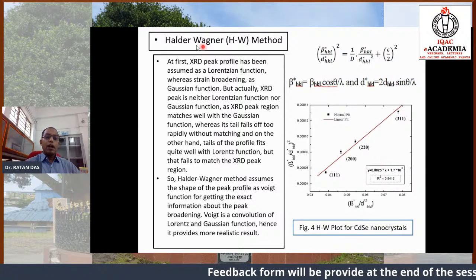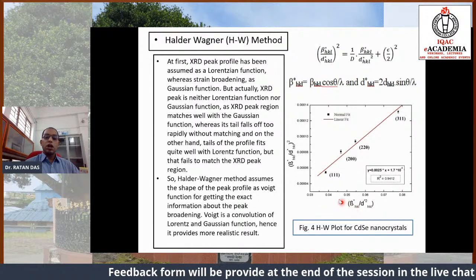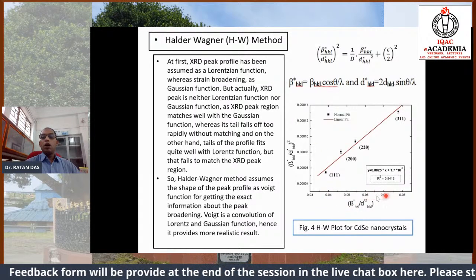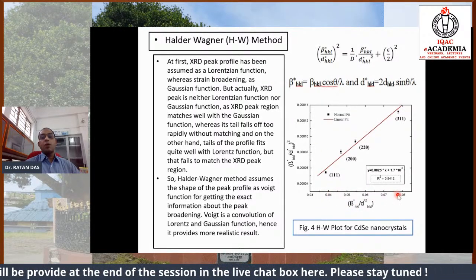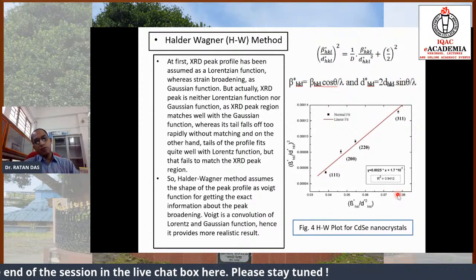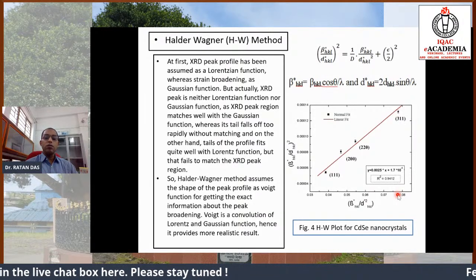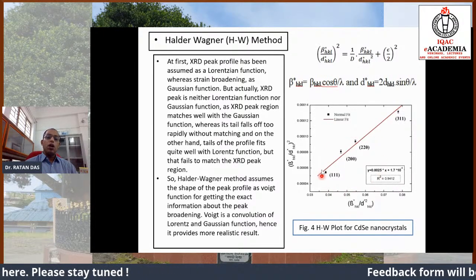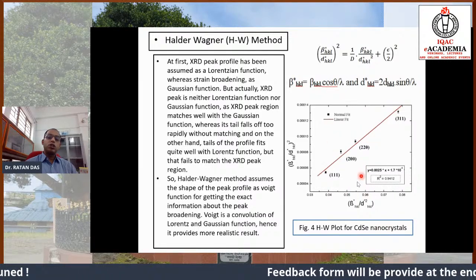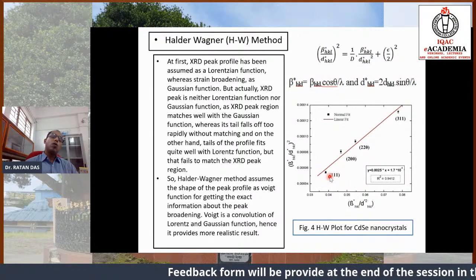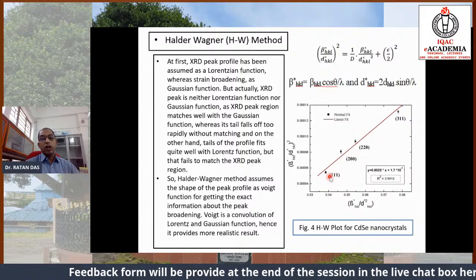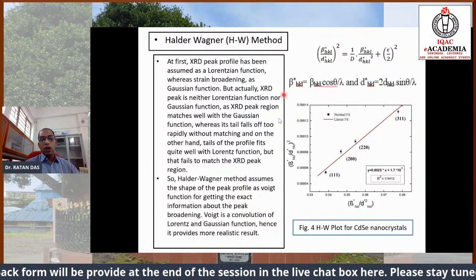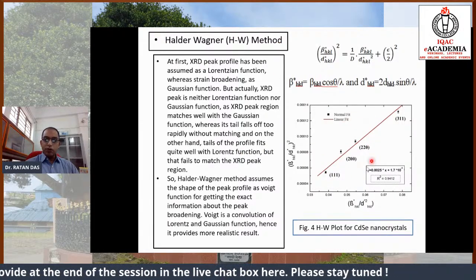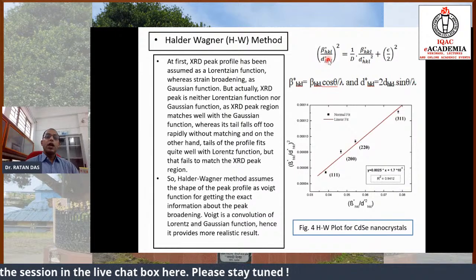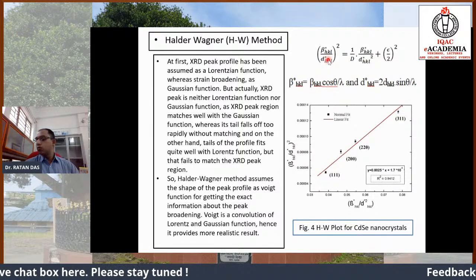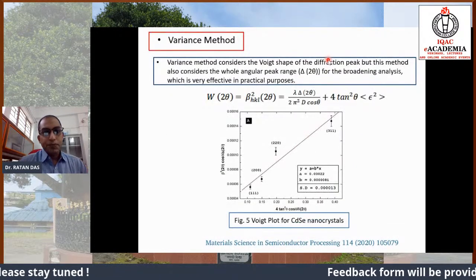But this particular Halder-Wagner method considers the lower angle diffraction pattern perfectly, but the higher angle diffraction pattern it does not consider generally. That's why if the diffraction pattern has all the diffraction peaks in the lower angle side, then Halder-Wagner can suitably be applied. And because of this, Halder-Wagner provides greater details about the strain value in the X-ray diffraction pattern.